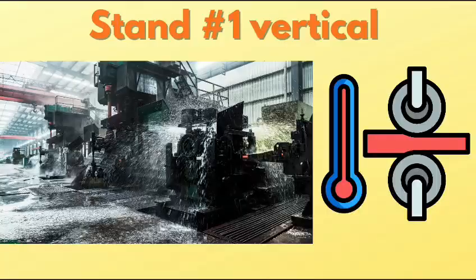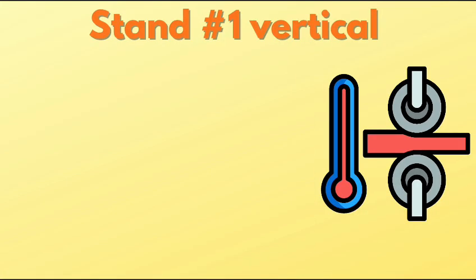The vertical stand has two vertical rollers, both rotating in opposite directions. The hot billet passes through the center of the groove. Because of the rotation, the rollers grip and pull the billet forward. The billet size reduces from 130 to 110 mm, a reduction of 20 mm. Force is applied to the sides, converting the square to an oval shape. Billet speed is 2.2 meters per second.